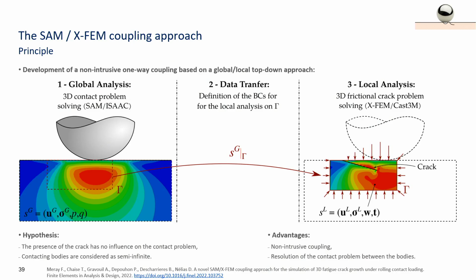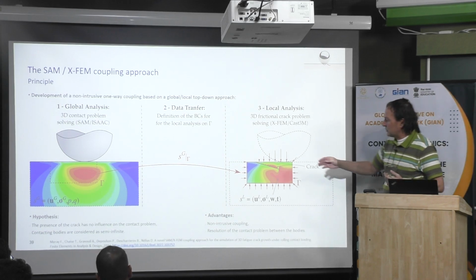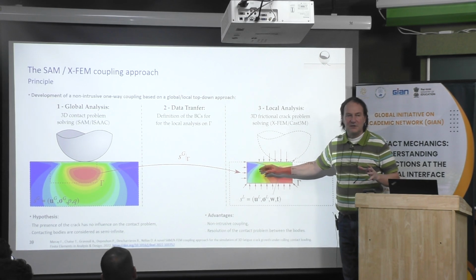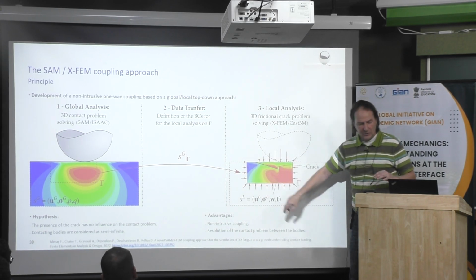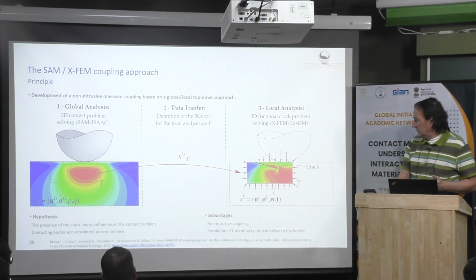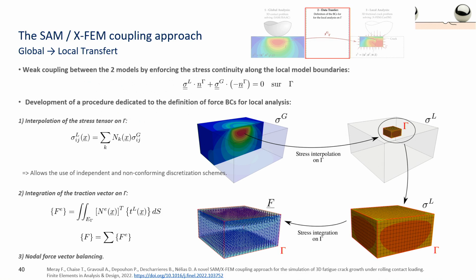Okay, then the idea is to have the contact model, create a box. In the box, we put the crack. And now all the technique, the numerical technique, is to apply the correct boundary condition, okay? Which is not really easy, in fact, because we have nodes, we have a surface of elements, and we have to transfer all that. Then on the surface of the box we are using, we should be in equilibrium. Then each time we have the traction vector that we calculate on each side of the box, and to be sure that this is equilibrated.